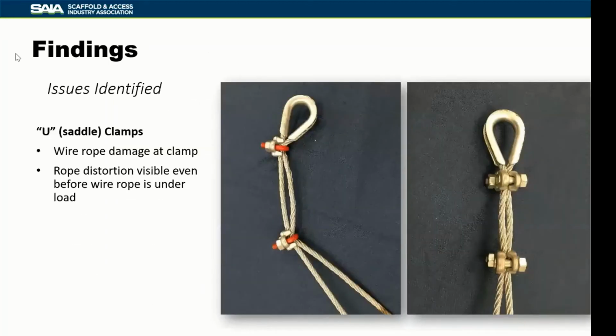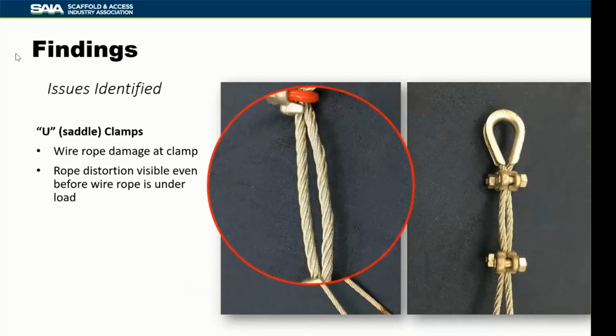So looking specifically at some of these that did not perform as well as we might like, looking at the U saddles or the U clamps, there was visible distortion in the wire rope even before we applied any load to the rope whatsoever. So you can see between the two clamps, before any load has been put on that, the wire rope is already starting to show some distortion.